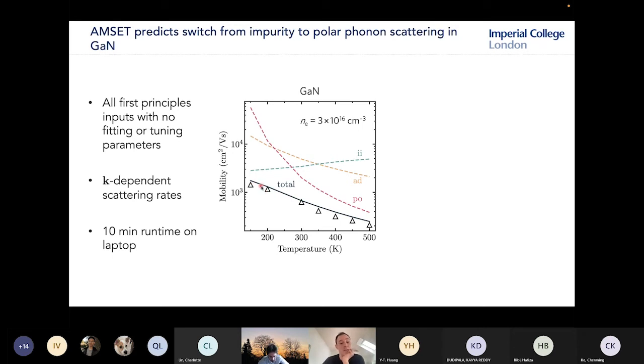So you can see that there's really nice agreement with AMSET across the entire temperature range. What's also nice is that we can decompose this mobility into the contributions from the individual scattering mechanisms. That's what I'm showing here by these colored lines. This teal line is the mobility if we only consider ionized impurity scattering. And then here, this is polar optical phonon. You can see that there's a crossover between these two mechanisms at about 300 Kelvin. And in the experimental mobility, we also see a change in the slope around that point as well. So I think it captures the experimental results quite nicely.